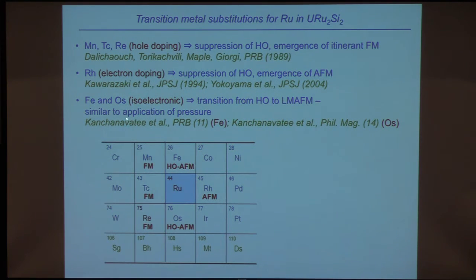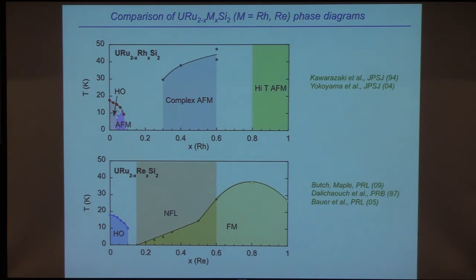And then more recently, we found that substituting iron and osmium, which is an isoelectronic substitution, produces a transition from the hidden order to the large moment antiferromagnetism that's very similar to what happens under pressure, okay? And so let me just show you the rhodium and the rhenium cases. Again, I'm not going to go into any detail, but for rhodium, you see hidden order here, antiferromagnetism, and then this gap where nothing particularly interesting occurs. Then you get complex antiferromagnetism, another gap, and then high temperature antiferromagnetism.